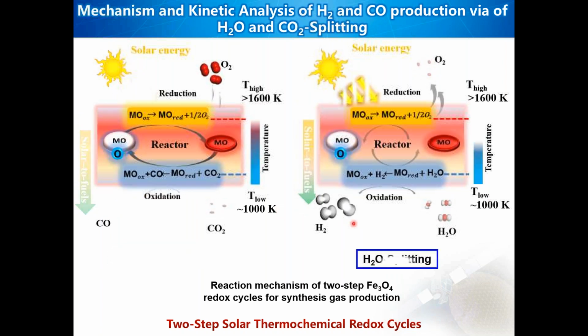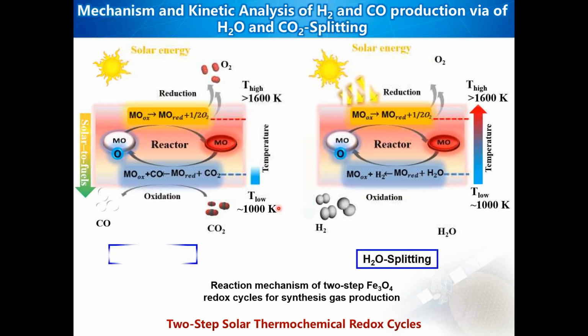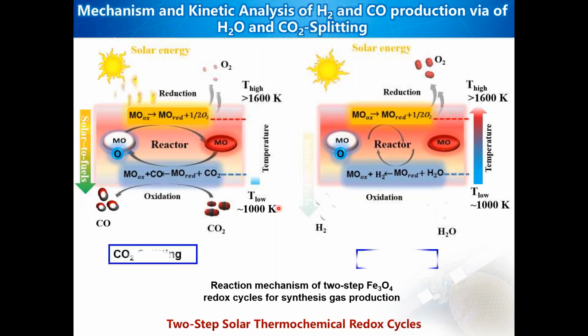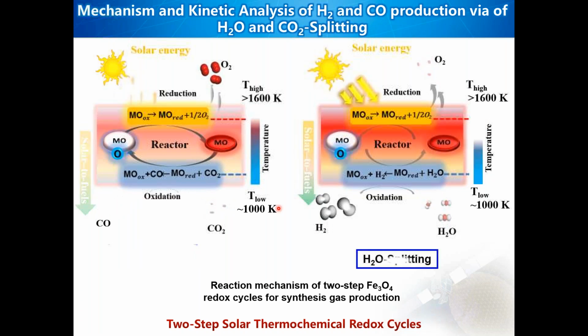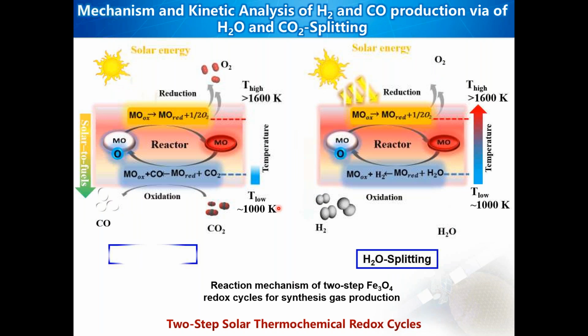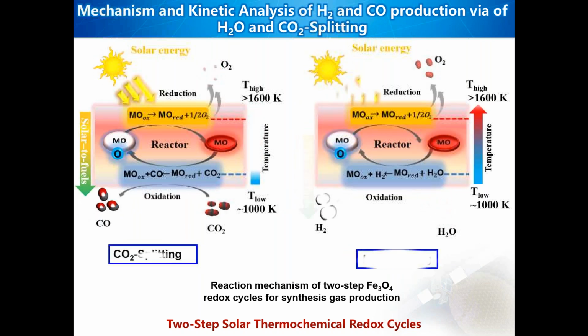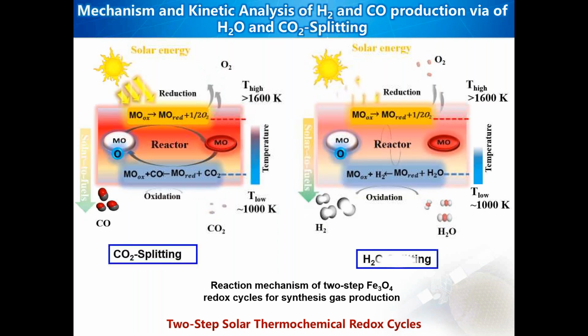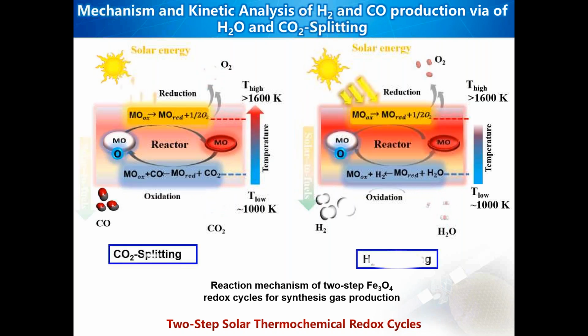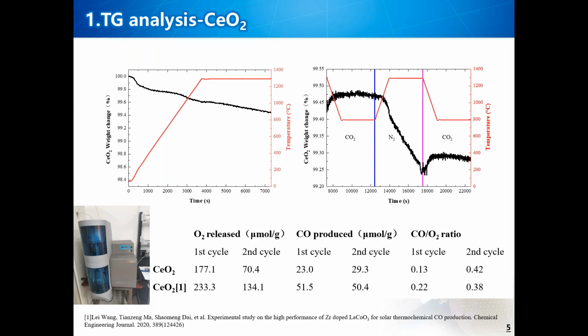Although this process can effectively produce solar fuels, finding a catalyst or redox material that can facilitate the process with high efficiency and selectivity, as well as integration into a solar conversion device, remain the key problems. Therefore, we try to screen out more suitable oxide catalysts by thermogravimetric analysis. In the TG experiment, two thermochemical cycle tests were carried out for each material, and blank tests were conducted to eliminate the influence of carrier gas, buoyancy, and other factors.